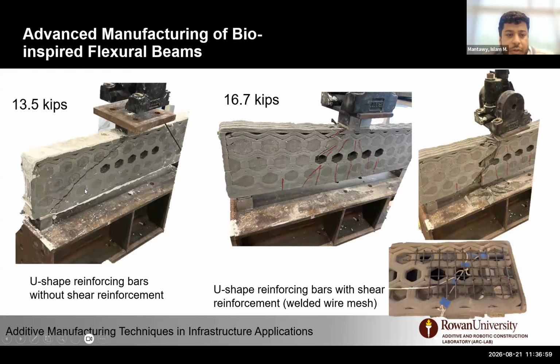On the left side, you can see the shear capacity of this beam was around 13.5 kips, and a nice failure that combined shear and flexure. And the middle one is dominantly shear, but it extends because of the load. It was 3-point loading. And the second one had shear reinforcement, which was able to suppress shear cracks using the welded wire mesh. And we shifted from shear failure to flexure cracks and flexure-shear cracks.